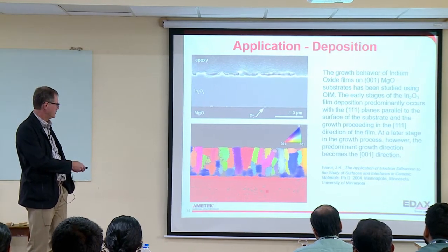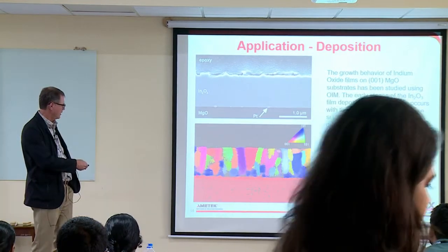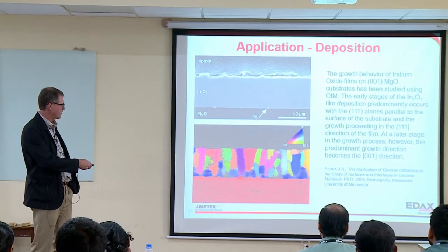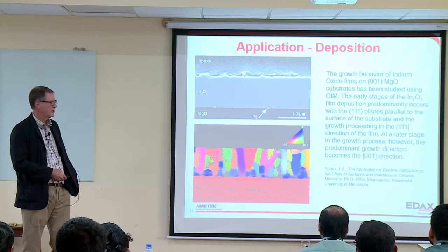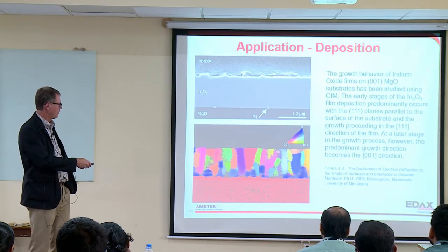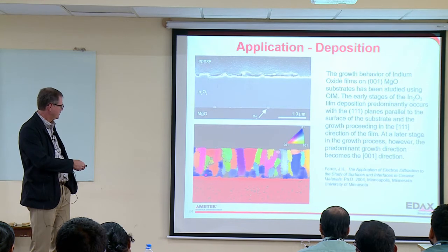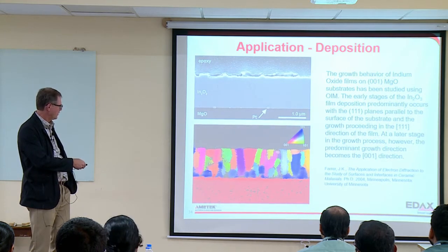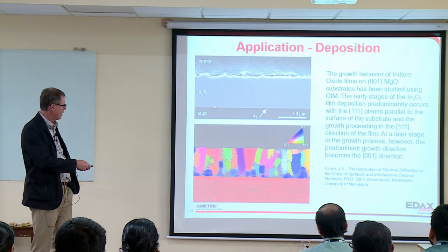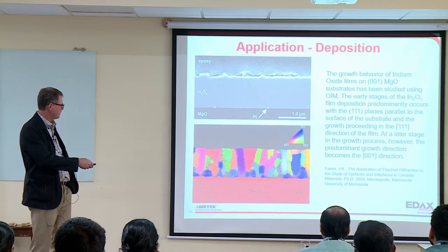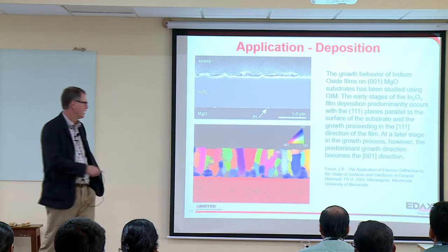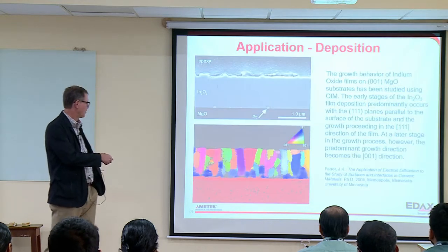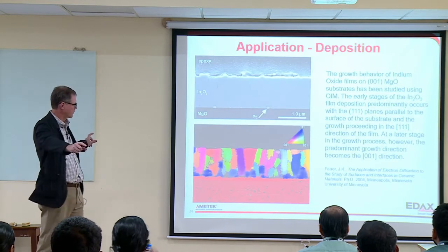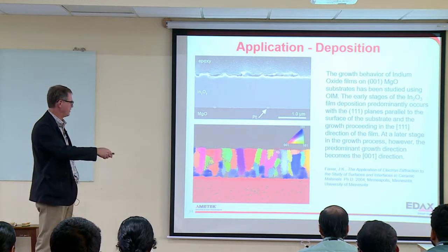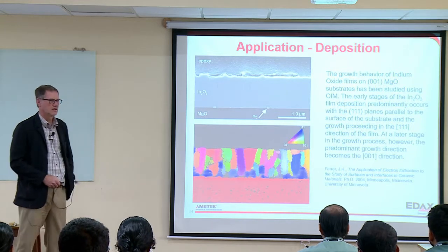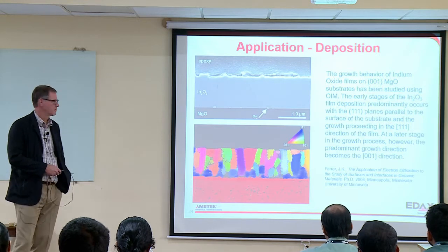And you'll notice this is red. So it's definitely not an epitaxial growth or nucleation. You actually get 111 nucleation. But as these grow, there are a few 111 types, these red, close to red, and they're the ones that grow. The growth of these blue ones tends to get pinched off and replaced with those grains. If you look over the whole structure, you'll see it's really dominated by red at the surface and blue at the beginning. So it's an oriented growth mechanism.